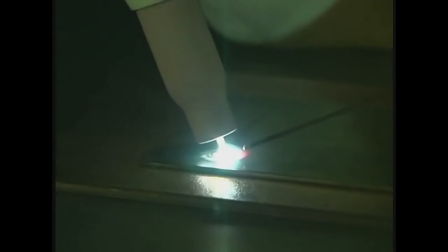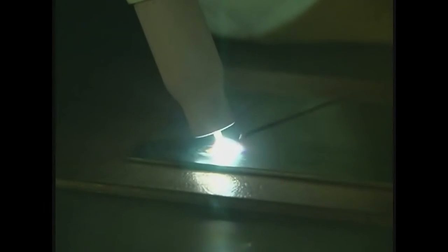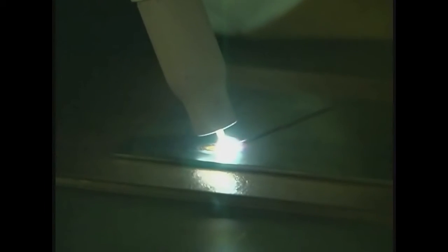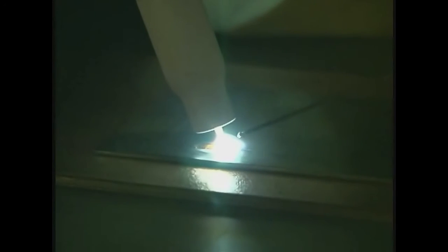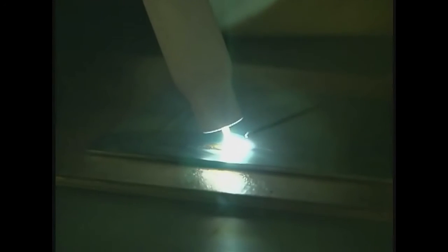When adding filler rod, I'm not shooting for the center of the puddle. It's better to just touch the filler rod to the leading edge of the puddle. The puddle will draw in the proper amount of rod. You don't have to stuff a lot of rod into the puddle. When withdrawing the rod, be sure not to pull it back too far. You want to keep the hot end of the rod inside the envelope of the shielding gas.